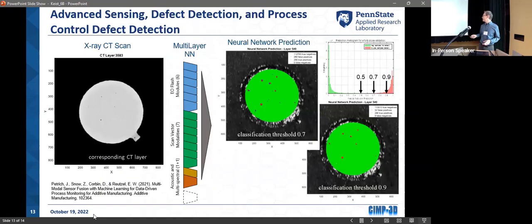And so what do you do with this data? Well, you can get over terabytes of data from one of these builds, and then that really becomes an issue with how do you understand all this data and do some type of analysis of it. This is work by Jan Petrich at ARL with help of Steve Corbin and old student Zach Snow and my colleague Ted Reutzel of using neural network processes to help predict issues or defects within the build. So in this case, these are small cylinders, roughly 12 millimeters in diameter that we built. This is a slice that we did afterwards by X-ray CT. And we noticed that we had some flaws. These are small little pores that came up during the AM process that we see here.